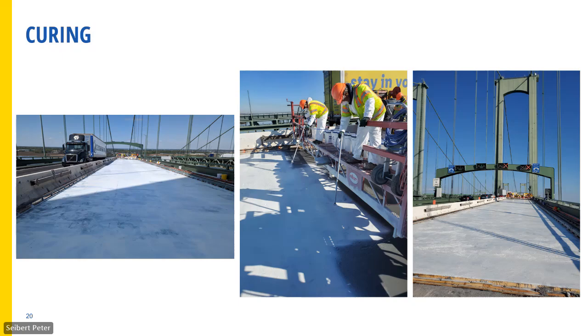And what would happen, especially on a bridge like this, where there's always wind, is those tarps would flap up and down and they would pull out, or you'd have to weigh it down with so much that you would make impressions on the UHPC. And that was troublesome to get out during the grinding operations. So we pushed and we innovated.